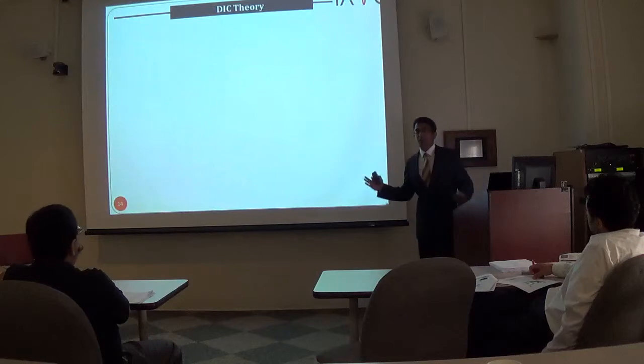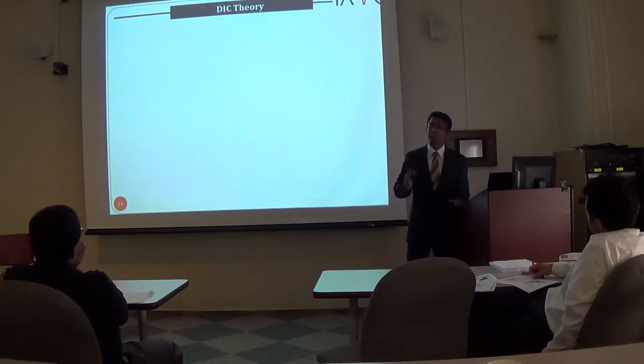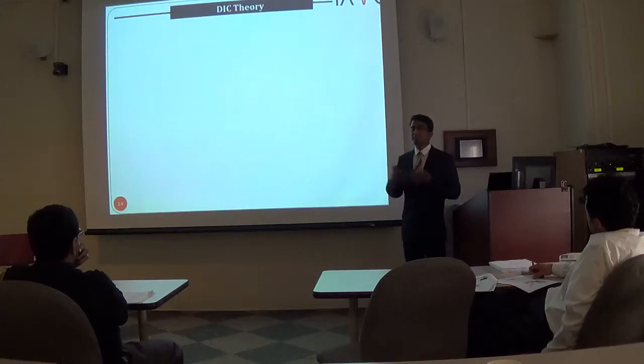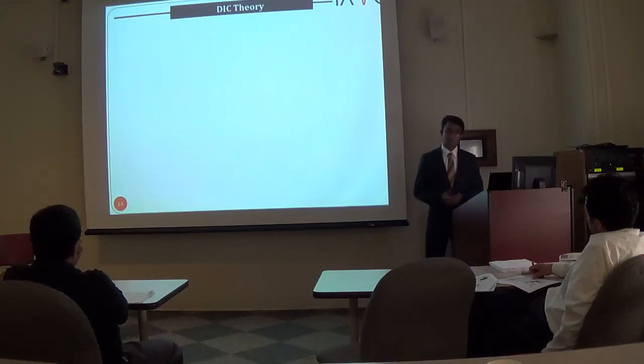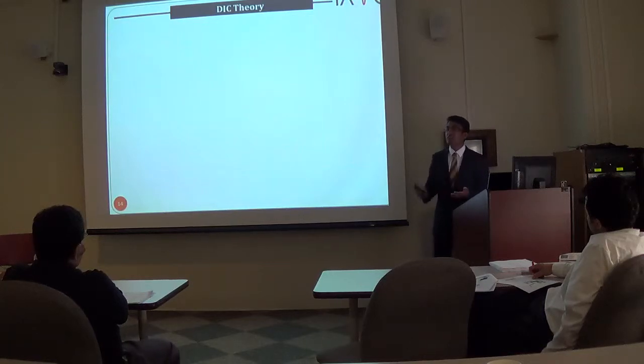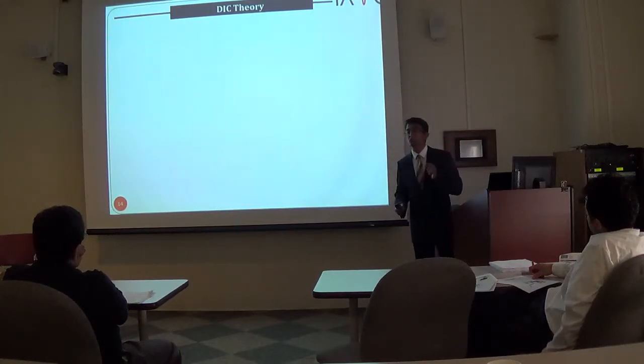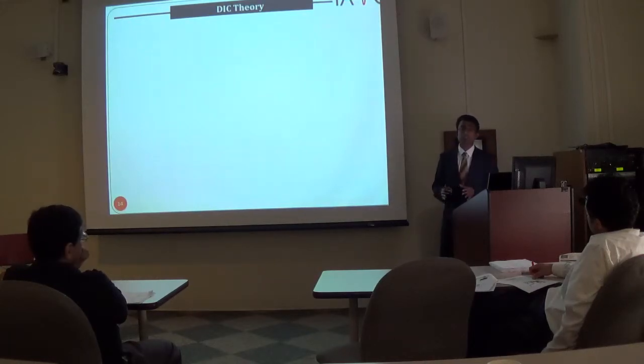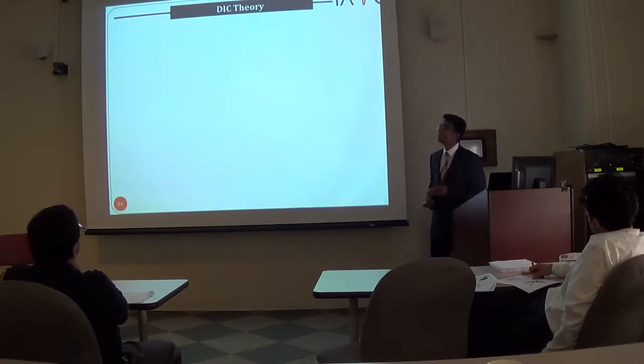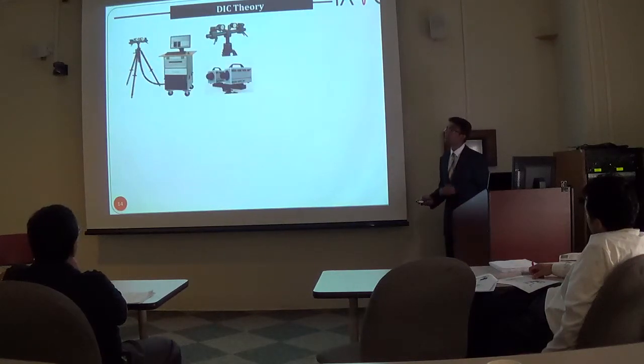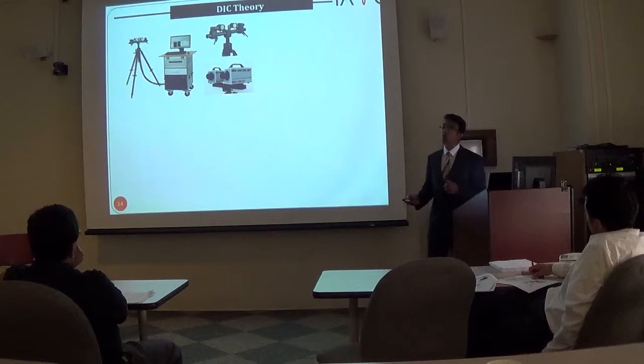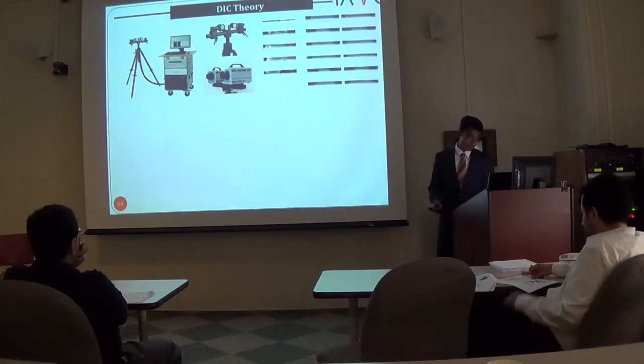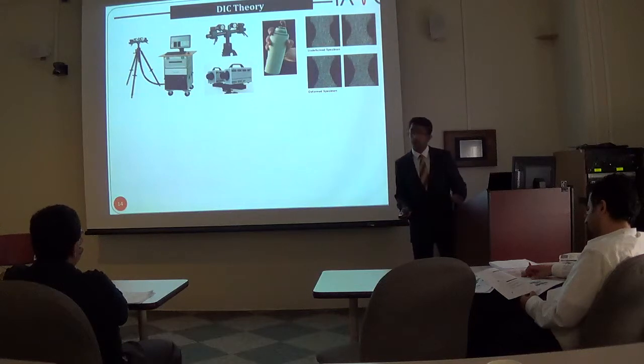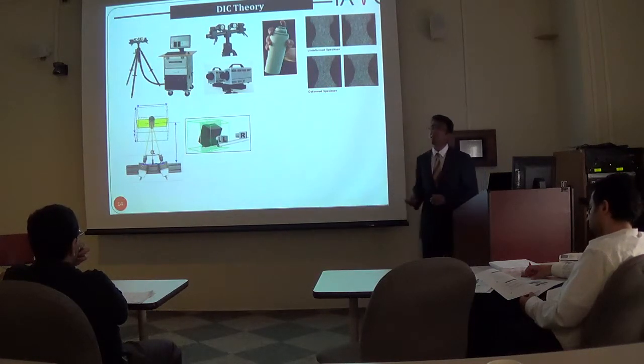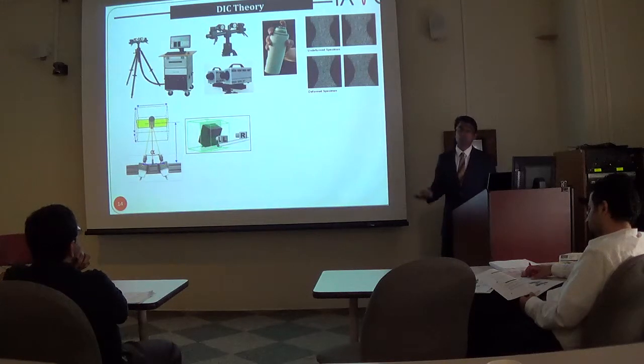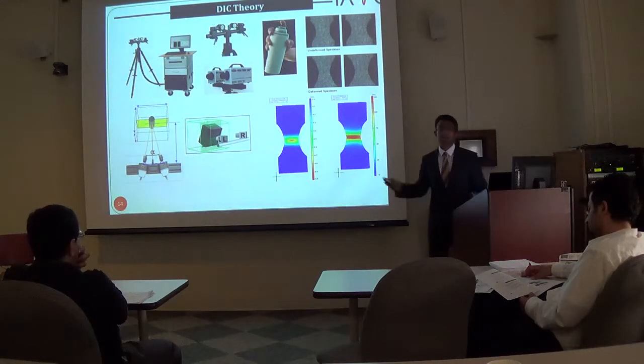That is in fact one of the main reasons that make acoustic emission a complex NDT phenomenon, and in certain cases very challenging for damage detection for field applications. Thus, in order to interpret, identify reliably and cross-validate the AE signals obtained during the test, a full field optical metrology technique was extensively utilized in this research, which is called digital image correlation. The digital image correlation is a full field optical metrology technique that measures the full field deformation and strain on the surface of the structure. A speckle pattern is applied on the surface, and stereoscopic vision is utilized to correlate images before and during the loading to obtain the final strain maps and the displacement maps.